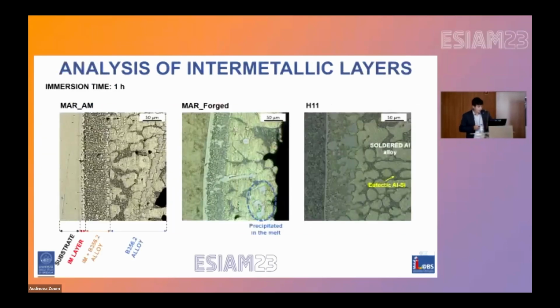The morphology of the different layers formed after the immersion test is presented in this optical microscope image. As can be noted, some common features are present for each sample. A dense intermetallic layer is present near the steel substrate, followed by a mixture layer composed of intermetallic particles and aluminum alloy. Then it's possible to see, on the soldered aluminum side, the presence of typical aluminum dendrites surrounded by the eutectic silicon particles. And furthermore, some intermetallic particles precipitated in the melt can also be recognized.